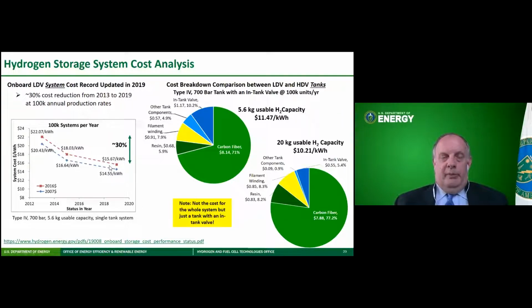So we go from about $16 to just under $12 a kilowatt hour when we do that. However, the carbon fiber has gone from a little over 50% to over 70%. So this gives us an idea of just looking at the pressure vessel itself and the tank valve.